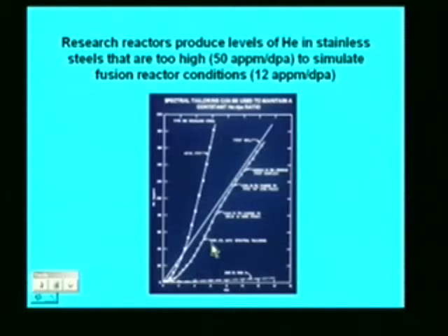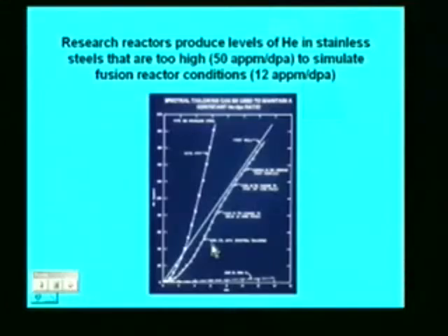Well, research reactors can be used to study helium effects because they have a high thermal flux. And we talked about that two-step nickel reaction, which will produce helium. And here's a case where we're going to exploit it to our benefit. We're going to intentionally produce helium in materials so we can study what will happen in cases, for example, of fusion reactions. Here we have a plot of helium generation as a function of displacements per atom. And the problem here is that research reactors can produce levels of helium in stainless steels that are far too high to simulate fusion reactor conditions. 50 atomic ppm per dpa as opposed to the desired 12.